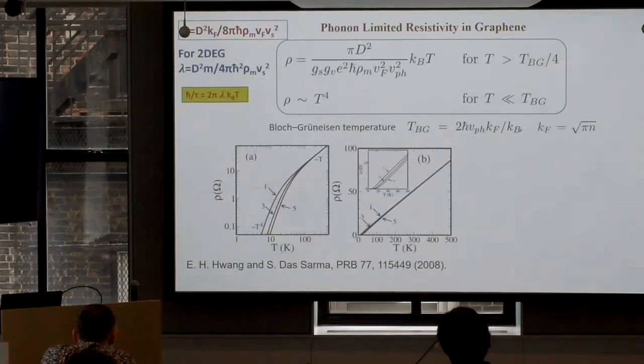What we did, we just did the first principles calculation of resistivity in graphene and Tc in graphene, monolayer graphene, because of electron-phonon deformation potential coupling. And you get the standard answer that you expect at high temperature. But this high temperature is not the Debye temperature. Often people in books use the Debye temperature. It's either the Debye temperature or the Bloch-Grüneisen temperature, whichever is smaller. In metals, the Debye temperature is much smaller than the Bloch-Grüneisen temperature because the Fermi momentum is so high. But in graphene, it's really the Bloch-Grüneisen temperature.